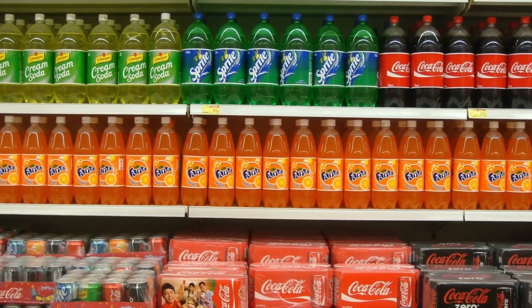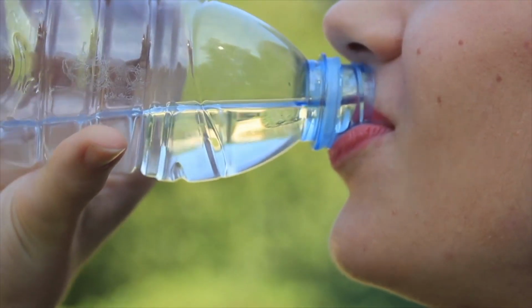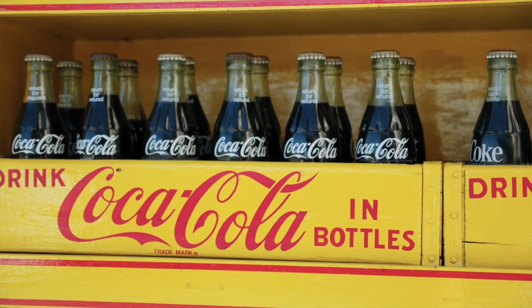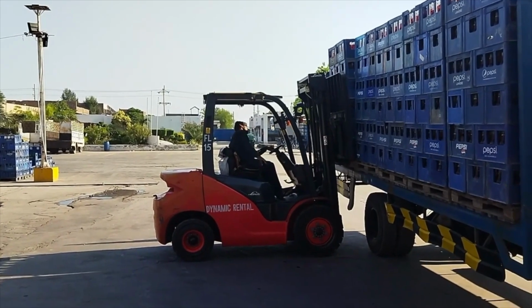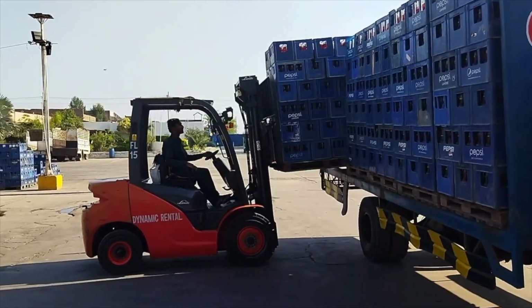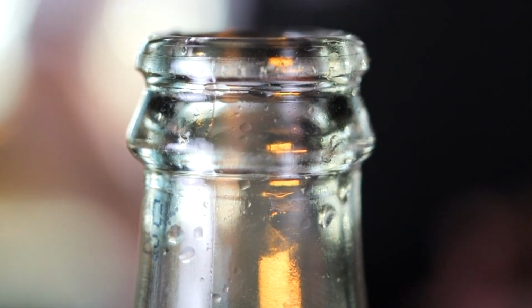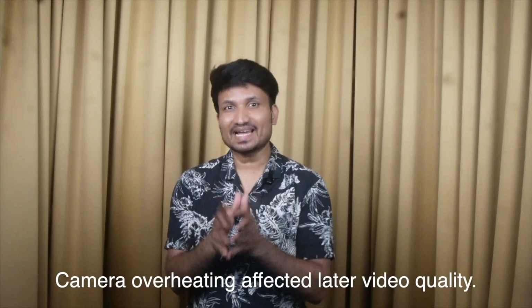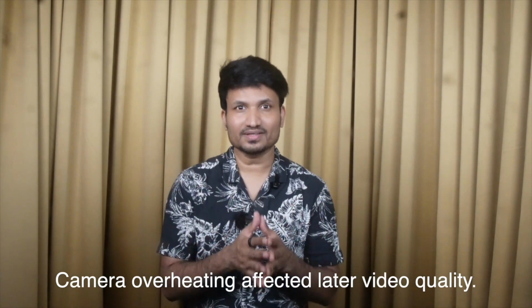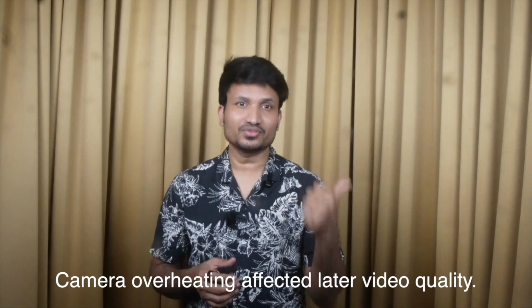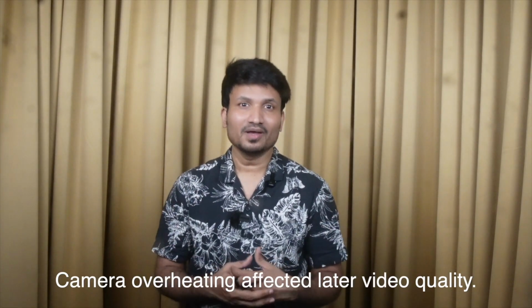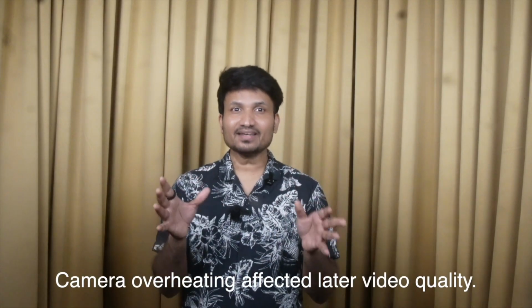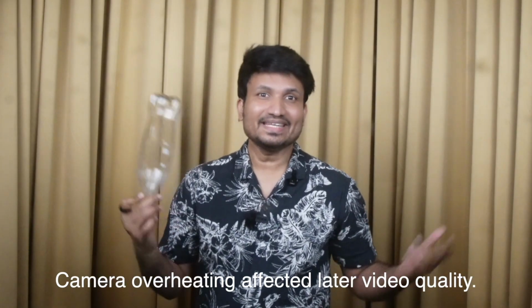Carbonated soft drinks in these plastic bottles are often single-use, filled and drunk relatively quickly. The glass is heavier and reused in many supply chains. Caps and crates experience more friction and handling before the bottle gets to you, giving more opportunities for paint to abrade. So in this specific experiment, for the size range they measured, glass bottle sodas and beers looked worse mainly because of the cap paint shredding, while plastic bottles' main problem moves into the nanoplastic range. And that the study flagged, but did not fully quantify. And that doesn't make plastic safe. It just means the dominant problem was different depending on the packaging.